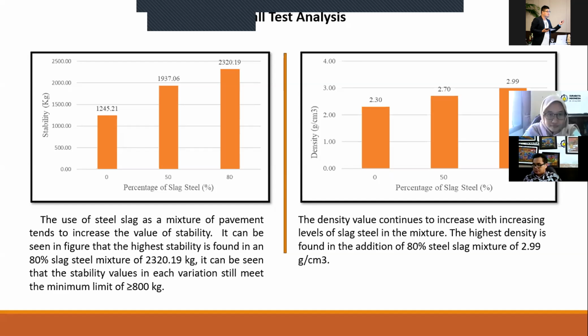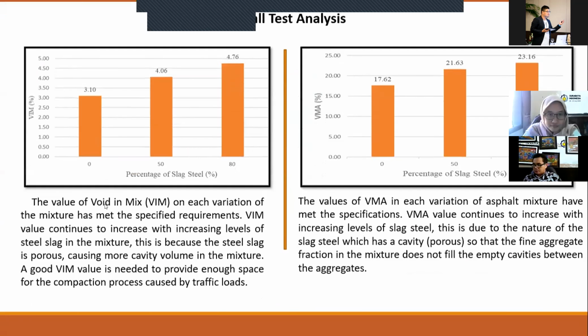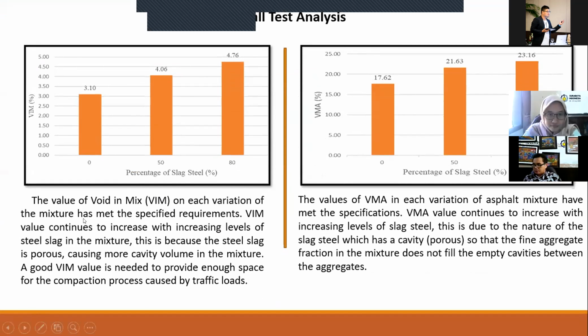It can be seen in the figure that the highest stability is found in the 80% steel slag mixture, at 2320.19 kilograms. It can be seen that the stability values in all variations still meet the minimum limit of 800 kilograms. The density value continues to increase with increasing level of steel slag in the mixture. The highest density is found in the 80% steel slag mixture, at 2.99 grams per cubic centimeter. The density values in all variations of the mixture have met the specification requirement.